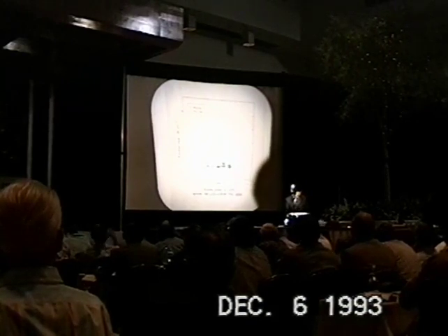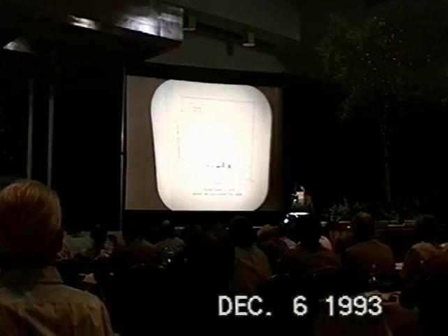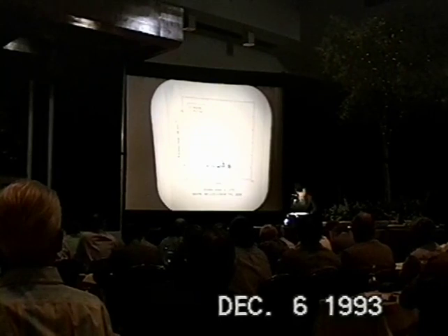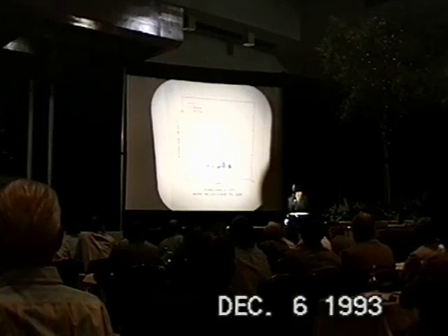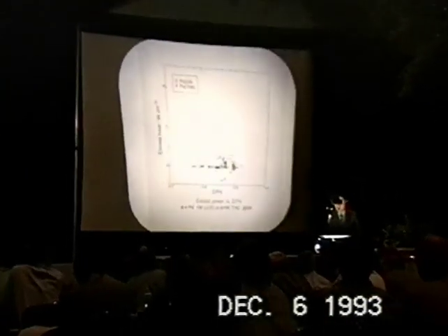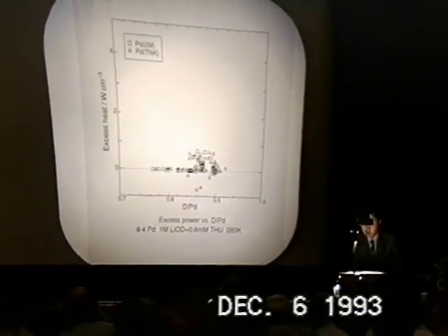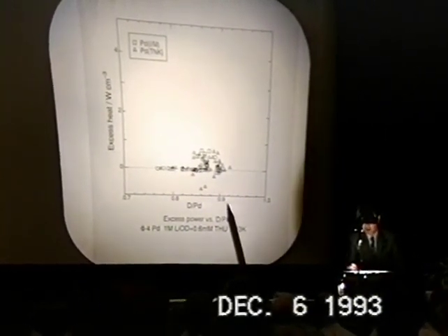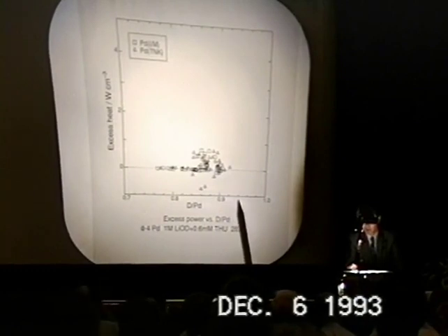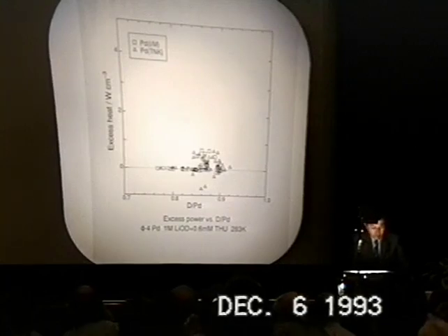time too. This is probably because the temperature goes up in the actual XRT measurement, while the temperature is kept almost constant at 10 degrees C in the loading ratio measurement. So probably the chemical absorption of tellurium is strongly influenced by the electrolyte temperature, and then we could go into the region of somewhere like 4.94 or 4.95, which we attained in the loading ratio measurement.